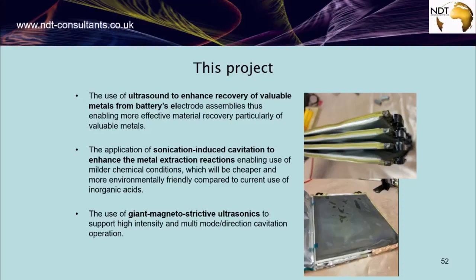So once we have delaminated the active material from the metal electrode, the next step is to leach, if necessary, the different metals from the oxide, separate them from the oxide and produce some salts, which the current technologies do as well, but they use very corrosive and very strong acids like sulfuric acid, and they heat at very high temperature. But by using ultrasound, we can do this at very low temperature, so much less energy is used, and we also don't need such strong acid like sulfuric acid. We can use just a simple organic acid like citric acid, for example. So two steps: delaminate the active material from the electrode, and the second one is to leach these valuable metals that we want to extract from the oxide.